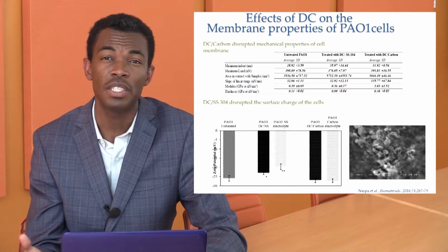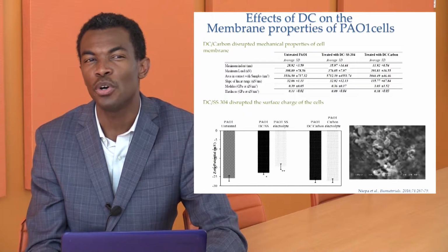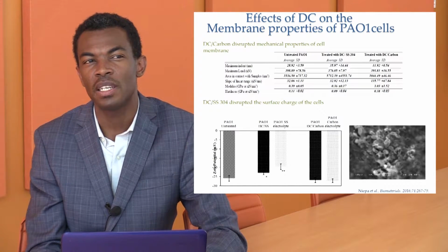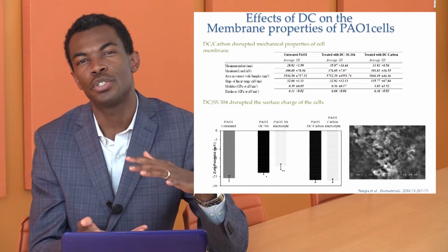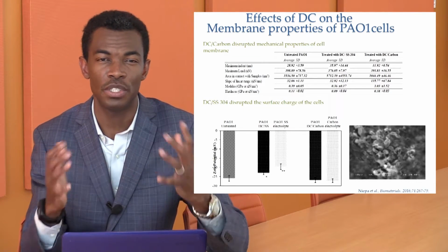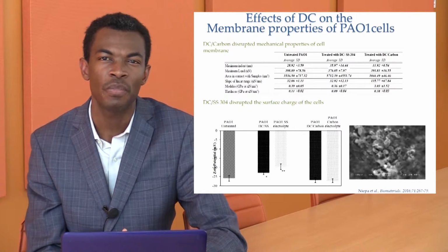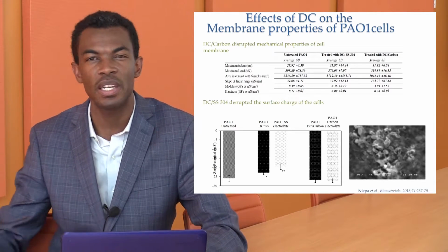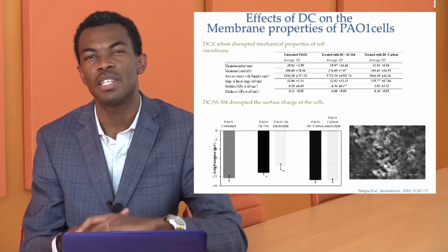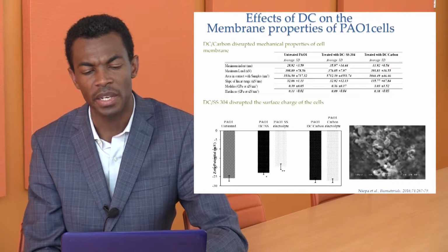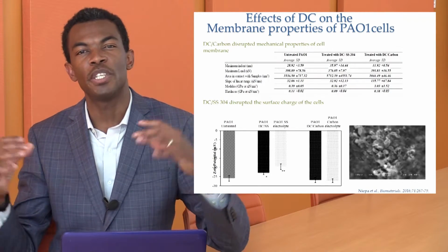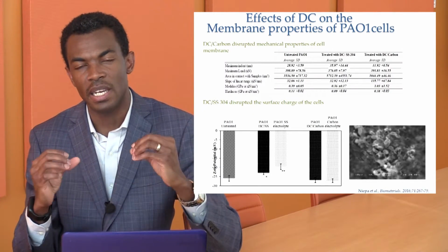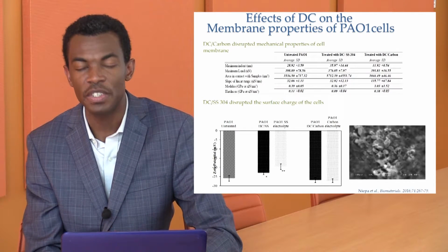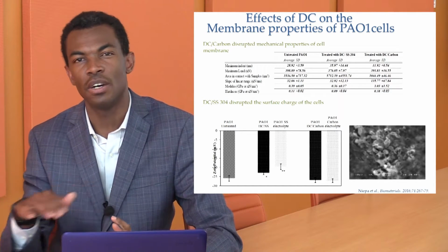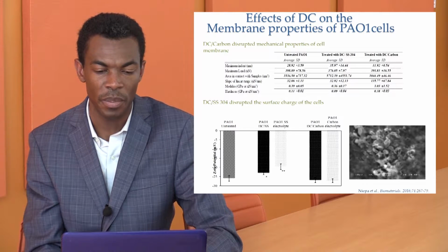On the other hand, the cells treated with stainless steel, the membrane potential or the zeta potential, which is the surface charge of the cells, did decrease. Instead of being greatly negative, it was less negative than it used to be for the control, meaning that the amount of metal cations that we're generating and that go on the cells allow the cells to have a very low membrane potential.